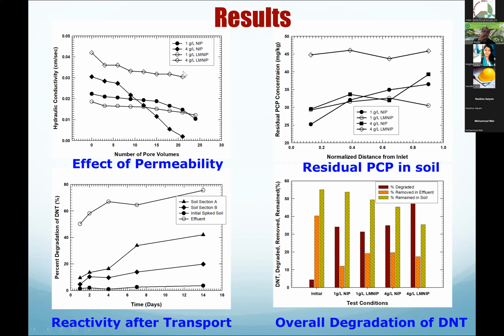So the concern about clogging up the pores by these particles is not a concern if you modify it with lactate. So we did some experiments. Here is the time and the percentage degraded in the soil sections. We looked at that one, and what happens to the residual contamination?